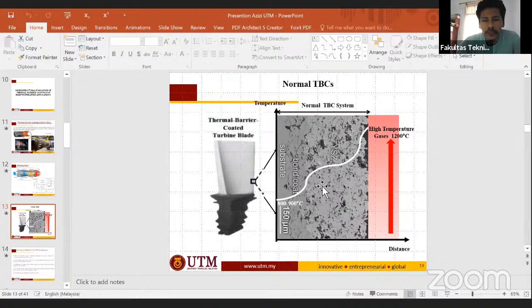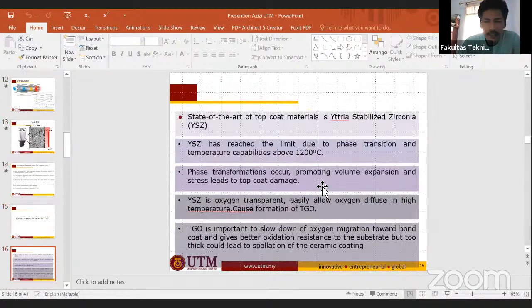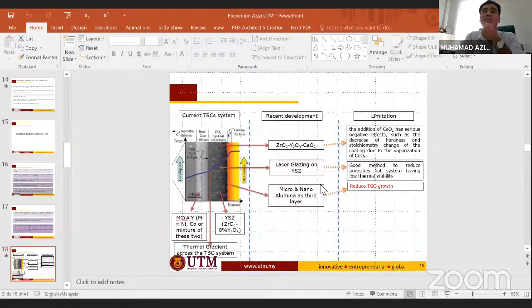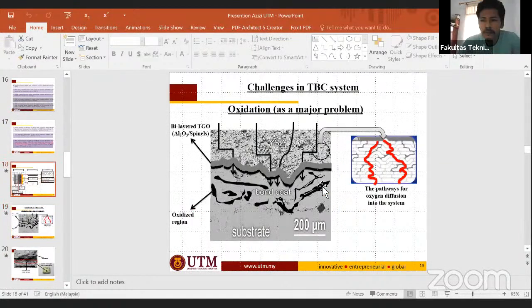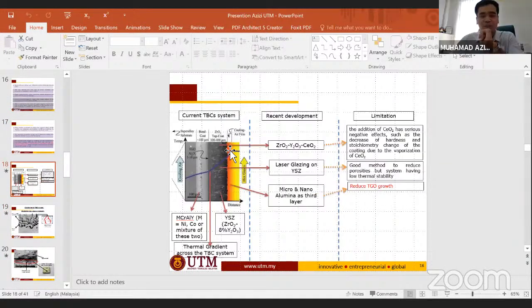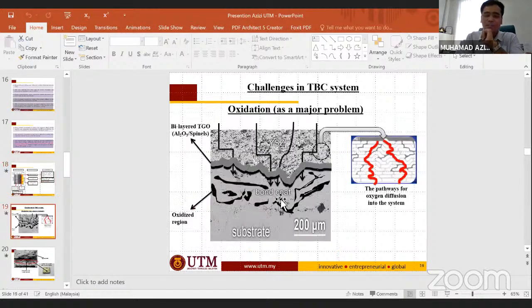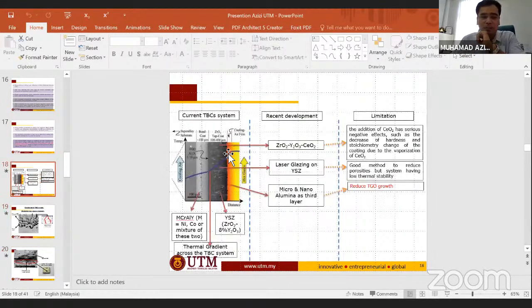You said that in order to close the porosity, you use this, what do we call it? The laser. Actually, we have two approaches. One is that we add another layer on top, a more dense layer, which is a nanostructure layer. And another is that we use the laser to seal. The laser will seal the porous structure here. They will seal, like we close the pores, so we can prevent the diffusion of oxygen.